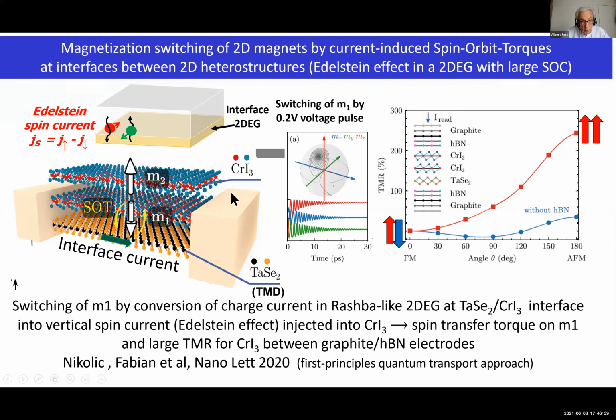And so an example is given by this theoretical paper on this bilayer, a CrI3 bilayer with antiferromagnetic coupling between the two layers. This bilayer is deposited, in this theoretical paper, on a 2D TMD, tantalum selenide (TaSe2). At the interface there is a 2D electron gas which has some Rashba property. So a strong spin orbit coupling gives rise to a Rashba interaction in the two-dimensional electron gas. And the Edelstein effect, in this theoretical description, by inducing a spin current into the first layer of CrI3, is able to reverse the magnetization of this layer.